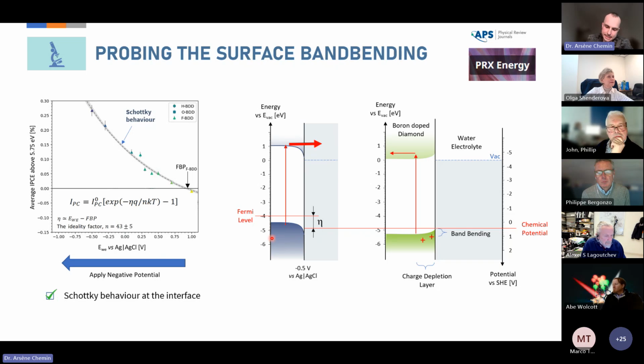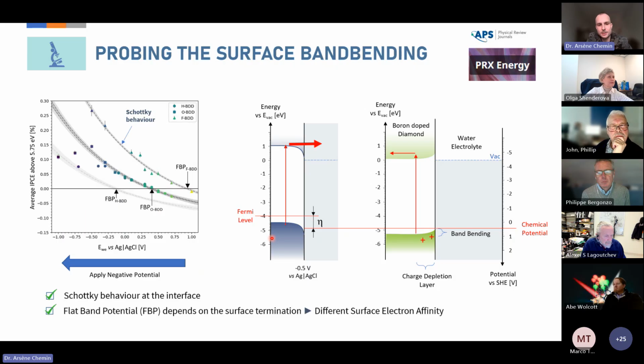And what was quite amazing in this study is that we changed the surface state of the diamond. The first curve I showed you was for a fluorinated diamond surface. And here we have the curve for the oxidized diamond surface. You can see that the behavior is the same, but the flat band potential is not. From what I told you, it's actually very easy to understand, because if you change the surface state from fluorine to oxygen, you will change the negative electron affinity at the surface of the diamond, meaning that the position of the band versus the vacuum level will shift. And this will also shift compared to the chemical potential of the liquid. So basically, the potential you have to apply in order to obtain flat band will not be the same depending on the surface termination.